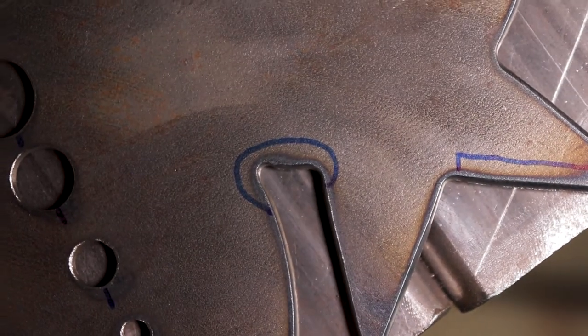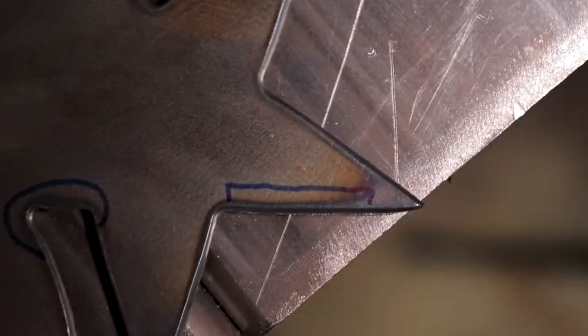If you think of the plasma jet, as a lot of you guys know it's pretty much shaped like a teardrop. I think what happened is either somehow in the settings I think the torch was set a little bit too high either in how the torch height control was controlling it, and that might be one of the reasons that I'm having that problem. And just overall the 16 gauge sample had a few inclusions, a few areas where it looks like the torch kind of wobbled a little bit. So that's something I've got to look into as well, but if you guys have any ideas about what might have caused this in terms of looking at my settings please let me know.